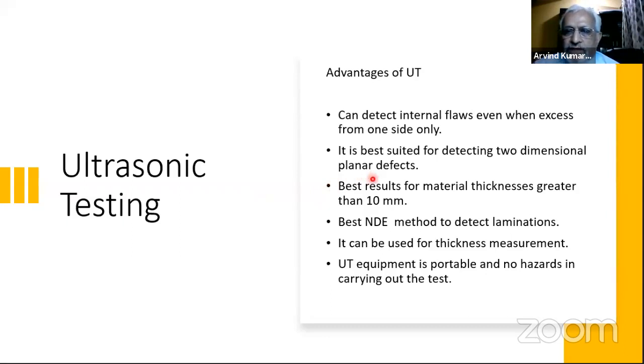So this is best suited for two-dimensional defects, as I said, planar defects like cracks, lack of penetration, lack of sidewall fusion. These are best picked up by ultrasonic testing. Material thicknesses from 10 mm onwards, it can detect very easily. And now advanced techniques and probes are available where you can go lower than 10 mm also. In fact, the AWS D1.1 code, which is for structural welding, allows UT to be done from 8 mm to 200 mm as per that code. 8 mm is the minimum thickness they allow.